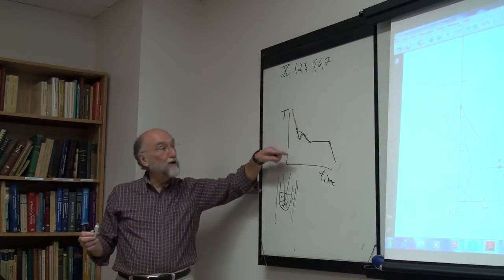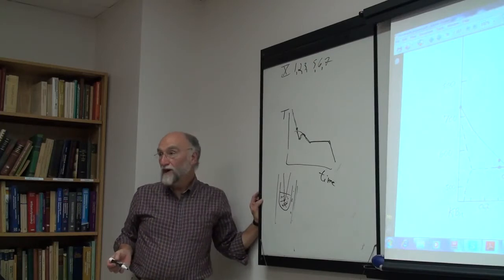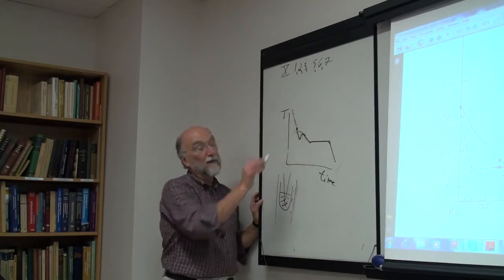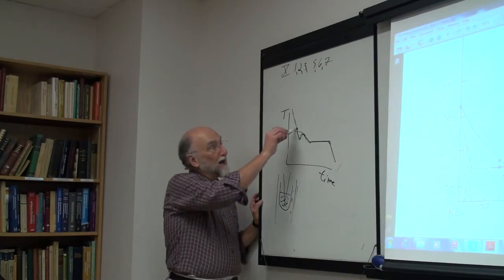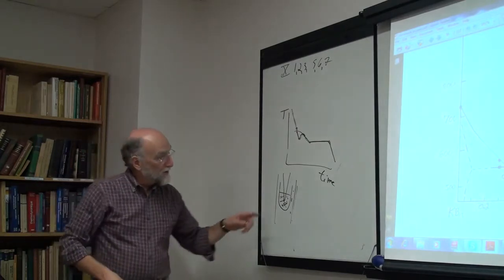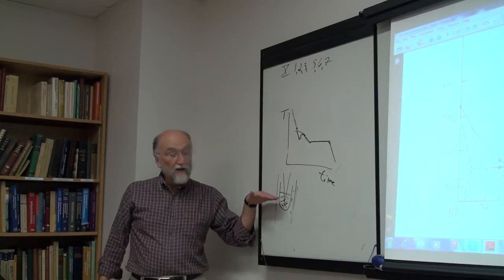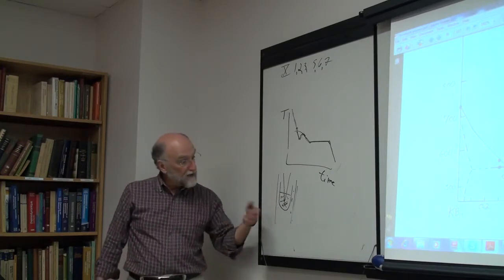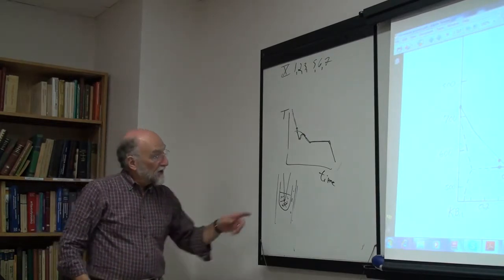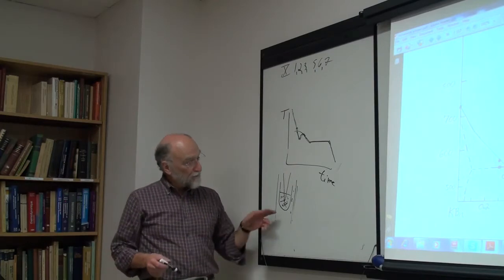If you get a little bit of experience with this sort of thing, you can get it back up to where it would have transformed. But it isn't evident, it's not a straight line, and it never comes back up to that temperature. You try to minimize as far as possible the amount of supercooling. One way of doing this, of course, is to be sure the sample is stirred. If there are temperature gradients in there, then you're going to have trouble too. So you keep it stirred to keep the temperature even. This is generally easier with a metal than with a non-metal like a salt or an oxide.